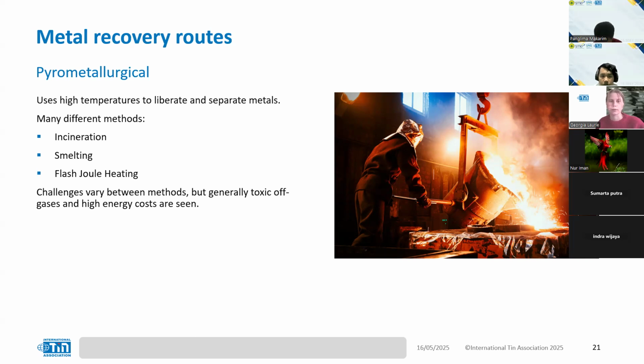By adding appropriate fluxes and reductants, the smelting process can be tuned so that valuable metals collect in the metal alloy at the bottom of the furnace, while other oxides of less value go into the slag. Industrial smelters can mitigate metal losses by operating under slightly reducing conditions and also capturing those furnace off-gases.